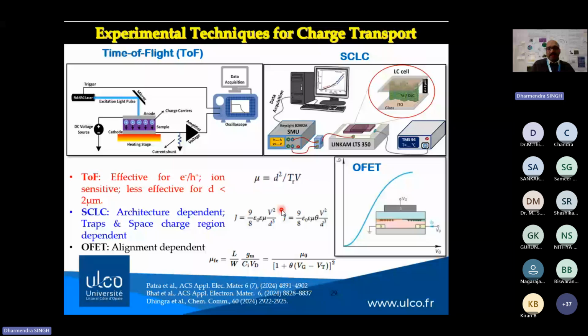However, it is very much dependent on the alignment. The higher the alignment, the higher the mobility, and vice versa. So if you do not have hands-on practice in the fabrication of OFET devices, you will not get very nice charge carrier mobility with the devices. If you are interested in learning these techniques, you can go through these papers in which these techniques have been reported for different organic